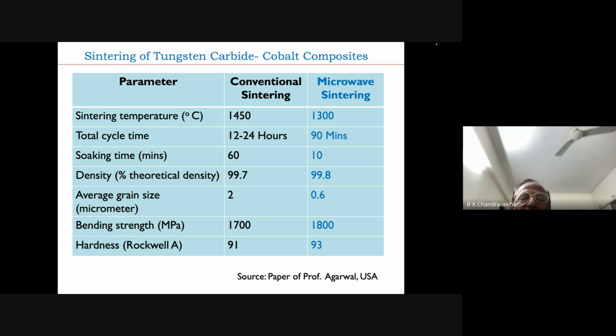Now you may say, what is the big deal about 150 degrees centigrade out of 1300? It has got a lot of implications, because as you go to higher temperatures, the cost of power increases tremendously. Going from 300 to 400 degrees, maybe 100 degree difference, the cost may be something, but going from 1300 to 1400, again a 100 degree difference, the cost will be many, many times more. As you go to higher and higher temperatures, the cost is very high.